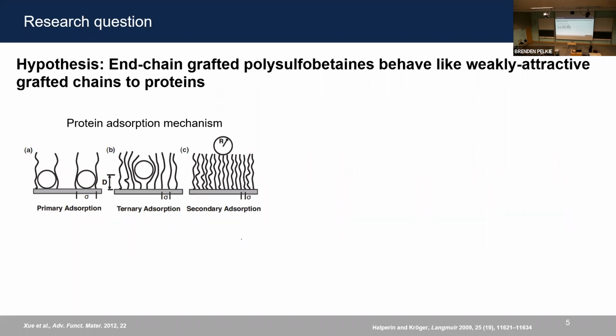In scenario C, when the protein is too big, so that the insertion penalty into the brush layer is very high for the protein to overcome, it can adsorb on the outer layer of the brush, which is known as secondary adsorption. And in an intermediate scenario, the protein is small enough that it can penetrate into the brush layer, overcoming the osmotic penalty. Then it starts forming attractive segment-protein interactions, which allow it to adsorb on the grafted chains.